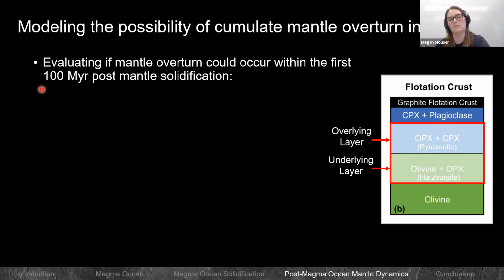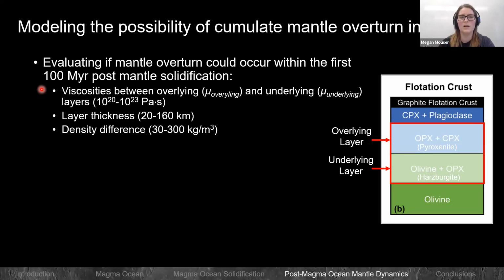So we're evaluating this within about the first 100 million years post-magma ocean solidification, because that heavily cratered terrain is the oldest terrain. So we need to see if this process is even feasible to get started within a reasonable time frame. So we're looking at a lot of different modeling parameters. We're no longer looking at viscosities of liquids, we're looking at them as solids, so they are significantly higher than what we had been previously looking at. We're also evaluating a wide range of possible layer thicknesses. The layer thickness relates to the overlying layer, in this case, the pyroxenite. So we're looking at a lot of extremes, from something that's very thin to something that's extremely thick.